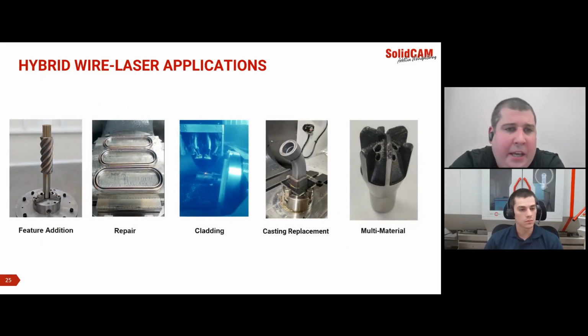And some of the applications that we find ourselves working on the hybrid side with these directed energy types of systems: feature addition, where we're taking a substrate, in this case a shaft, and depositing some material on that. So the bulk of the actual component might not be the deposited material. What this allows us to do is reduce the amount of cycle time for printing if we can avoid printing a generic shape.